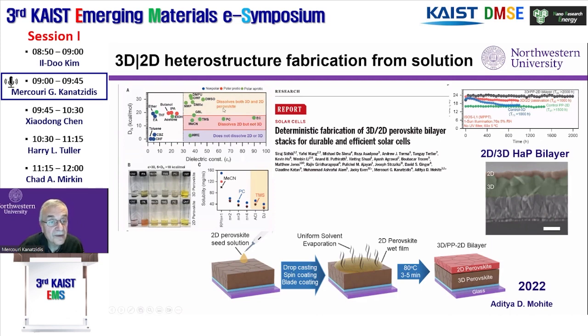And if you have very high donor number and high dielectric constant like DMSO, DMF, NMP, GBL, you can dissolve both. So that's no good. This is a sweet spot where you can dissolve one and not the other. So this allowed us to deposit a 3D film, and then on top of it, deposit a 2D without destroying the 3D. And so this is kind of a breakthrough because now we can have hetero-layered devices, and these